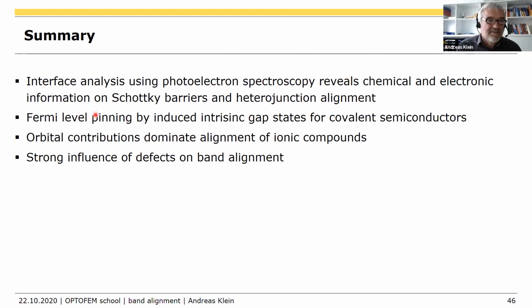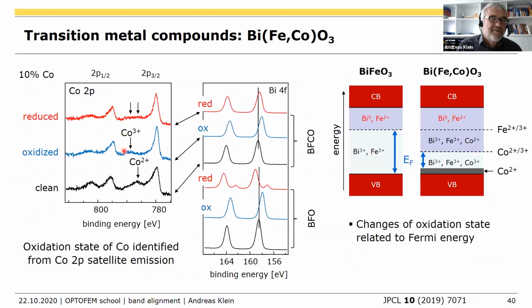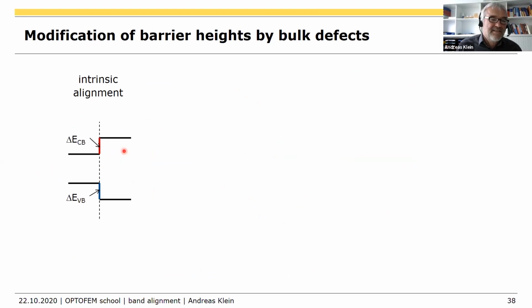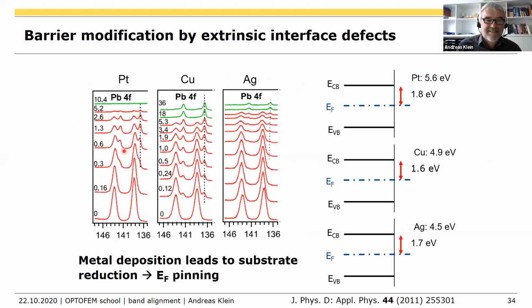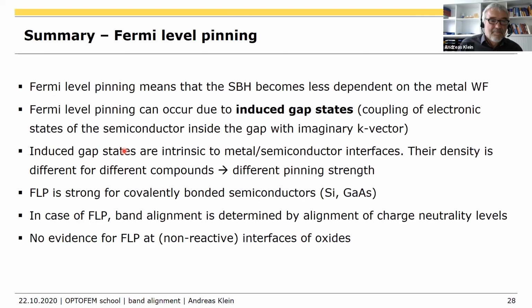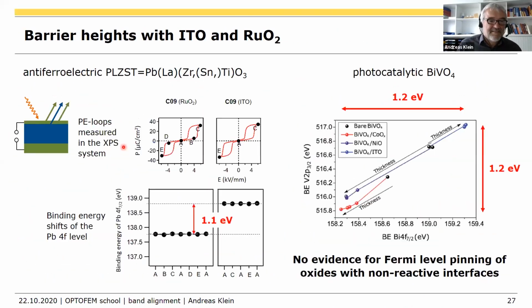In order to do so, you need to intentionally change polarization. We can do that. It's here. This is where we change polarization, and you see there was no change. For the bismuth ferrite, because we don't have a metal contact on top, it's not clear. We can in principle not exclude the polarization, especially when we oxidize and reduce the surface.